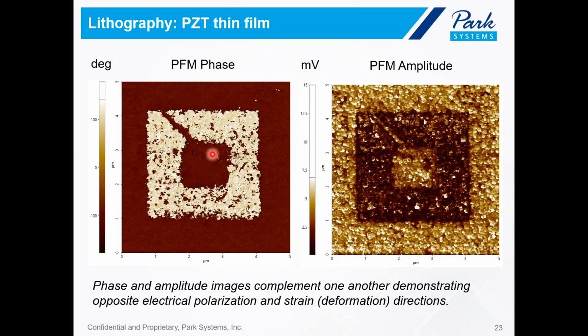So we can also look at the PFM amplitude signal. As I mentioned, PFM amplitude is the deformation of the sample. So here you can see that the bright region in the amplitude corresponds to the dark region in the phase.